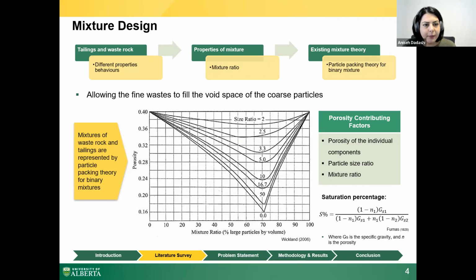As I said, tailings and waste rock have very different properties. So the behavior of the commingled mixture is dependent on the mixture ratio of the parent material. In this study, I used particle packing theory for binary mixture, which suggests that the fine waste fill the void space of the coarse particle for ideal mixture ratio. We call this condition just fill condition, the condition that all the voids are just filled with finer material. The just fill condition shows minimum porosity for the mixture.